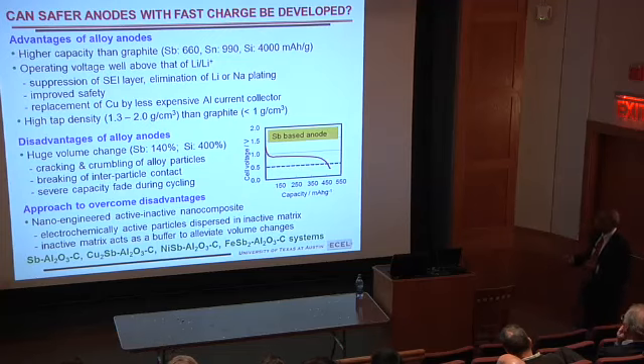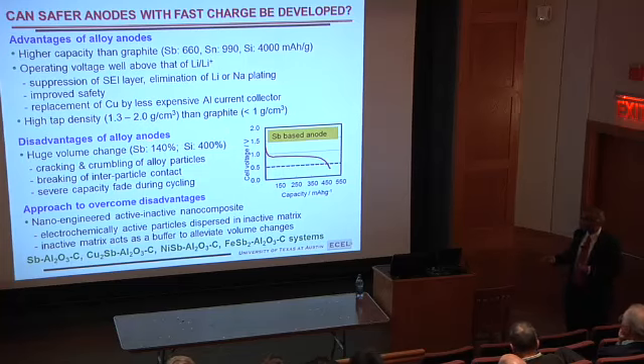Antimony, this is pure antimony voltage, around 0.8. So lithium will not be plated. I can charge, discharge fast without plating lithium. The sodium plating is much more than lithium plating because sodium voltage is even closer. So sodium plating can be avoided, lithium plating can be avoided with this kind of anode. The problem is big volume change.